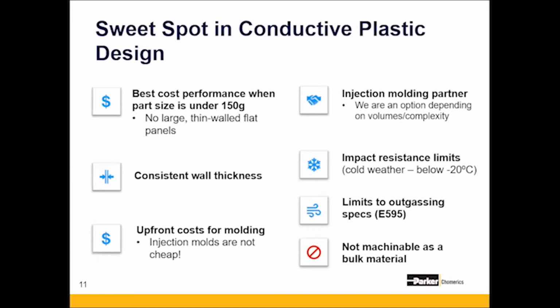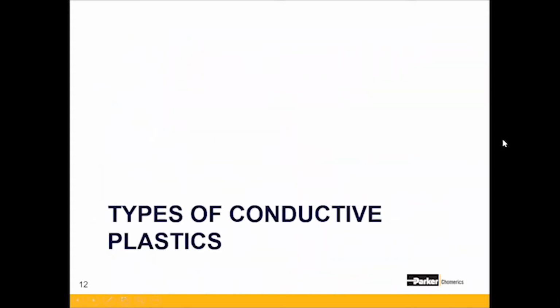And finally, the last little point to point out on the sweet spots of conductive plastic design is that we actually don't recommend molding a bulk sheet or machining pieces of conductive plastics. And that has to do with the variation in fiber direction once you start machining the parts. Yeah, you want to make sure that the conductive fiber is always parallel to your wall thickness. And if you're molding a block and then you start hogging out that block, you just can't guarantee that. And as soon as the fiber is perpendicular to the wall thickness, you start losing shielding effectiveness. So we definitely don't recommend that.